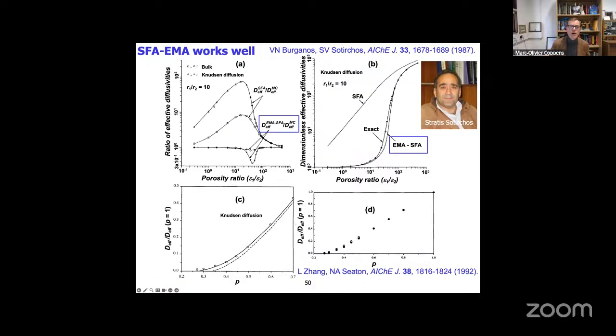I want to show this work by Stratis Sotirchos, who sadly passed away much too early, driven over by a drunk driver in Brussels once at an EU meeting. And he shows you how the effective diffusivity, both for bulk diffusion and even with Knudsen diffusion, if you combine effective medium approximation with a smooth field approximation, and you compare these broad varieties of pore networks with Monte Carlo simulation, you get really, really good agreement, except in some very narrow range.